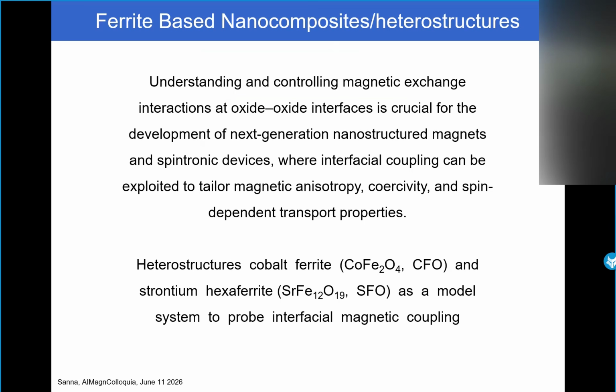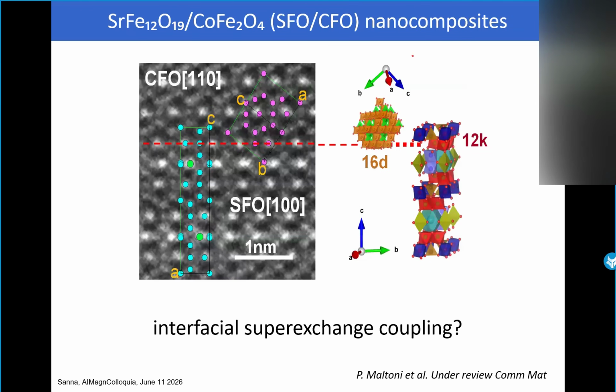So the nanostructure that we are considering is the cobalt ferrite combined with a strontium hexaferrite, which we are now using as a model system to probe interfacial magnetic coupling. So this is the system that we are considering, and we are going to see here CFO, the cobalt ferrite, and SFO, the strontium hexaferrite. Here, what is going to happen at the interface when we mix the 2 materials? Nanoscopically mix the 2 materials, atomically we mix the 2 materials.